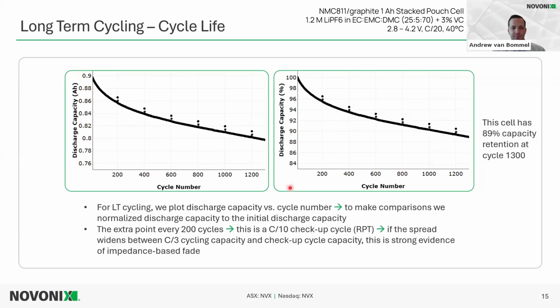Right here, you see an extra point every 200 cycles. So this is a checkup cycle or an RPT. So we know that this is done at a lower rate, a lower current, a slower rate than the regular cycling. So C/10 is here, C/3 is here. So we know if this widens between the RPTs and the normal cycling as cycling progresses, there's strong evidence of impedance-based fade. And sometimes the RPTs will be relatively flat, and then the regular cycling would be much below that.